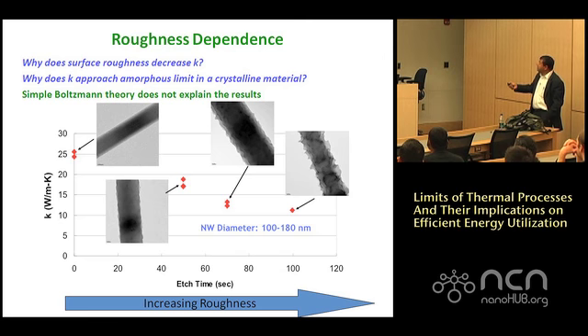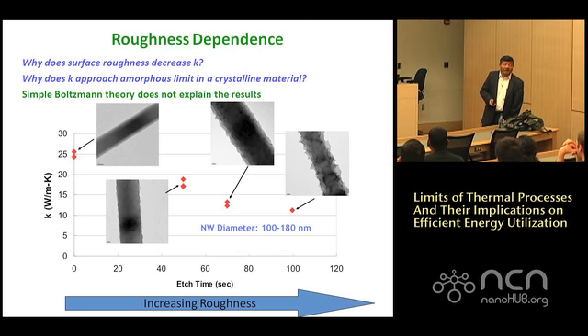So these are the TEM pictures. This is smooth, slightly rough. So we went from the VLS wire, which was really smooth, and started etching those instead of making just etched wires. And as you increase the roughness, yes, the thermal conductivity goes down. And that, again, Boltzmann transport doesn't quite explain. Question is why? And I would say we still don't understand completely.